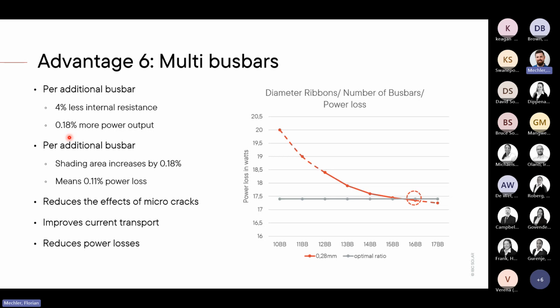Yeah, but of course, there should also be some negative points, because everyone would put the complete surface with busbars on it. So you can also say with every additional busbar, you have a shading area. And the shading area increases by 0.18%. And that means a power loss of 0.11%. And when you put it into a graph, you see it like here on the right side. You go to a boundary, and with 16 busbars, with a diameter of 0.28 millimeters, it's more or less the optimum number of busbars for it. So you get the best situation to get all the power out of the cells.